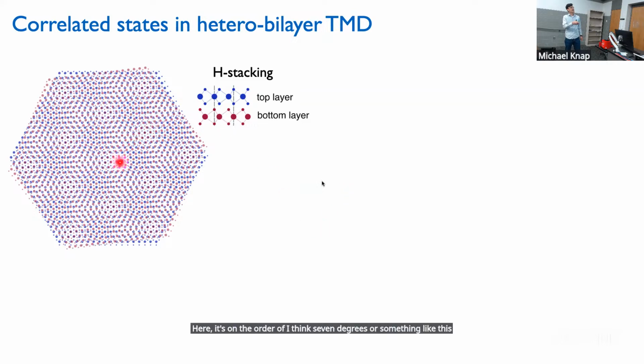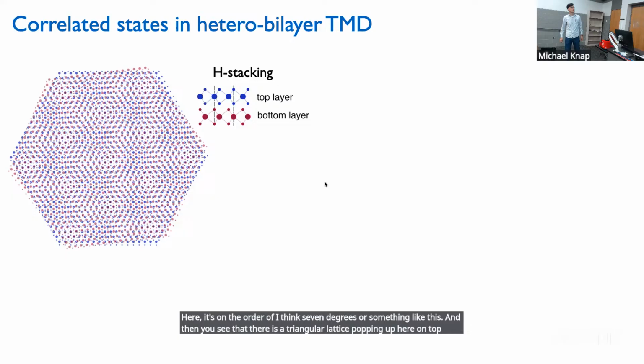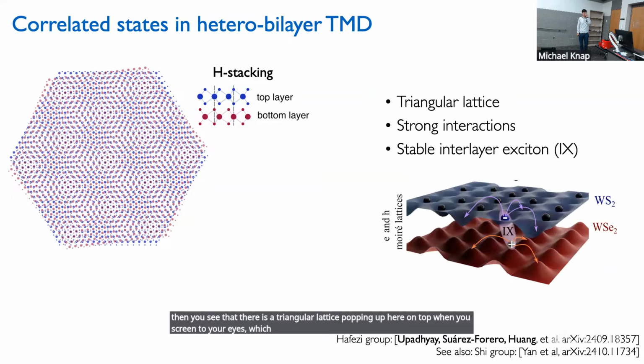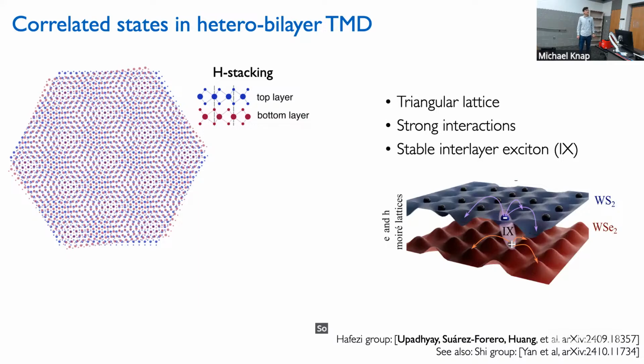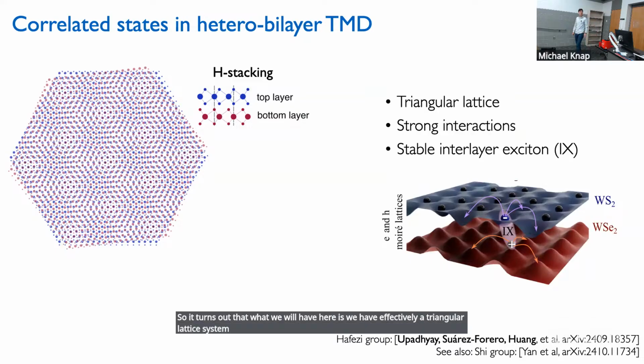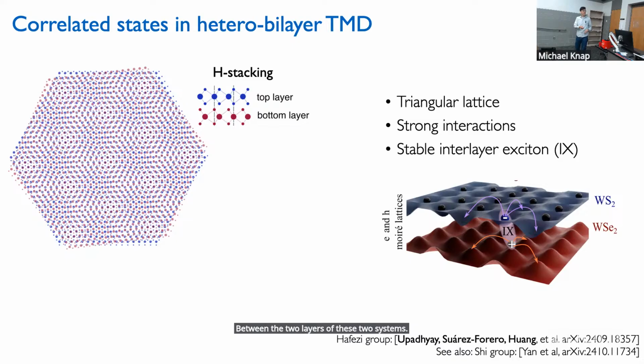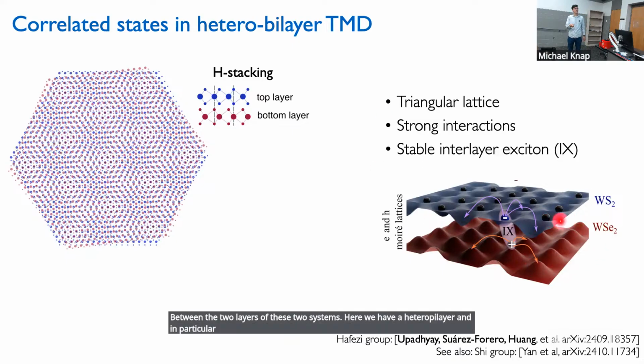And then you see that there is a triangular lattice popping up here on top when you squint your eyes, which is basically this effective description which is going on. So it turns out that what we will have here is effectively a triangular lattice system. We have strong interactions, and it turns out very nicely that one has now excitons which are a bit more complicated than the ones which I showed you before. These excitons are now interlayer excitons, so they are bound states between the two layers of these two systems. Here we have a heterobilayer, and in particular focus on the example of tungsten diselenide and tungsten disulfide, for which the experiments here in Mohammed's group have been performed.